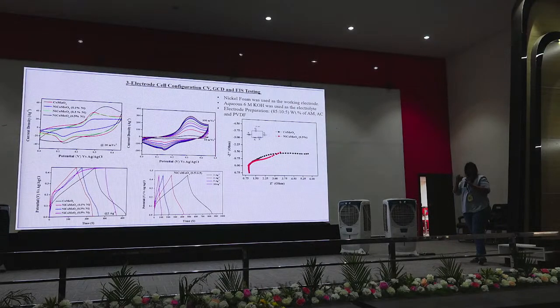0.5% of nickel and cobalt, this is the different GCD profile ranging from 1 ampere per gram to 10 ampere per gram. From this I have got a specific capacitance of around 450 Farad per gram at 1 ampere per gram current density. Coming to the EIS part, this is the EIS profile of cobalt molybdate and nickel molybdate.